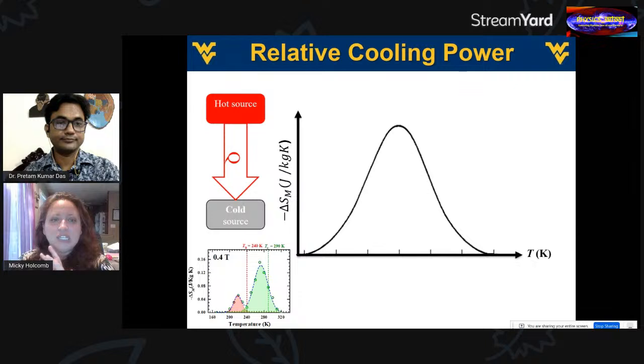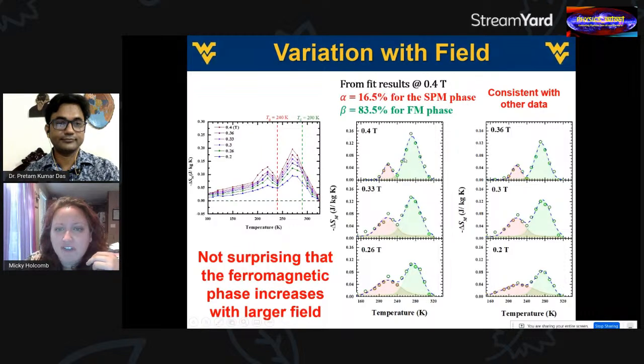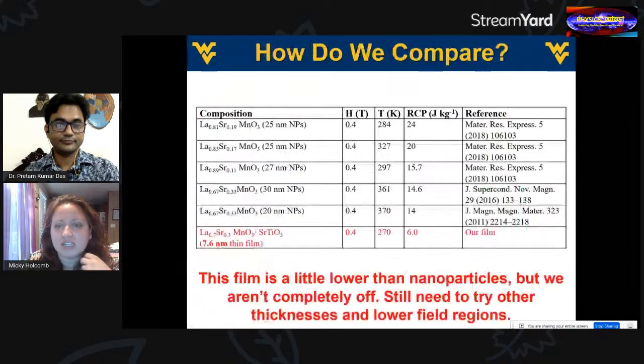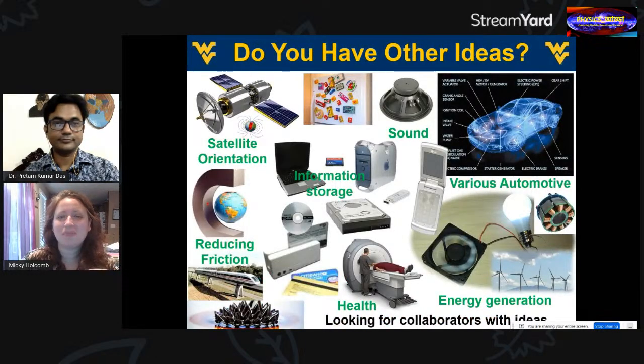So magnetic heating and cooling is a thing. We've been able to look at the relative cooling power in our samples. And basically that just looks at the full width half max of these peaks. So we can actually find that in our systems, and I'll just kind of speed up because I know I'm getting a little low in time. And for this first film that we've tried, we note that it's a little bit smaller than in nanoparticles, but I do want to point out that the nanoparticles that we've compared it to are a little bit bigger. So one of our next goals is to look at some bigger systems. We might have an advantage here. This is a significantly thinner film, so some potential promise in using this for heating, but I'm interested to hear other ideas if people have them.